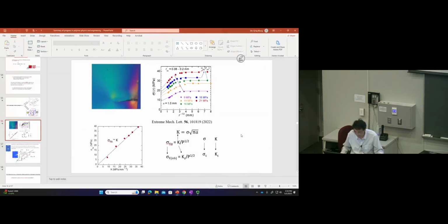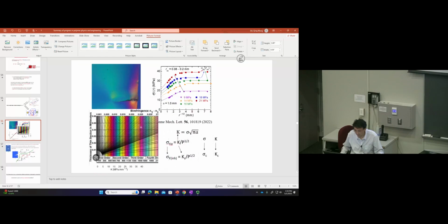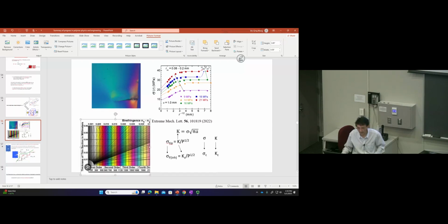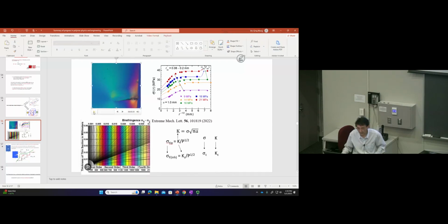In fact, what happens is if you start with the isotropic state, it's going to be black. So you're going to travel from black to gray. It's not very nice. So we could actually put a so-called retardation plate so that in the isotropic state, it's already in this blue region. And as you stretch, what you already see at once is there are butterfly-like patterns here as this thing is marching on. So it's marching on to here now.